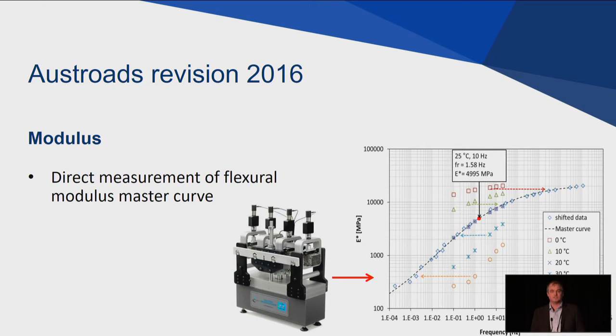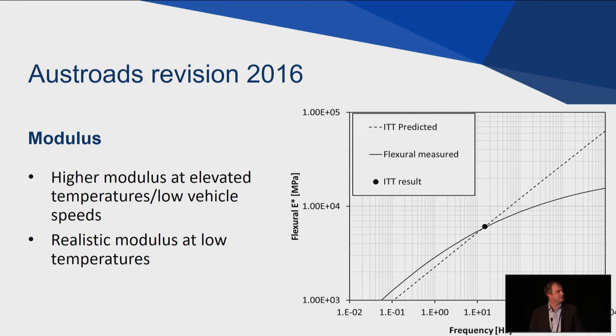So in terms of modulus, it is now possible to directly measure the flexural modulus and use the flexural modulus master curve in pavement design instead of those resilient modulus assumptions. And what that does is immediately reduce the pavement thicknesses for the pavement in the warmer parts of our country.